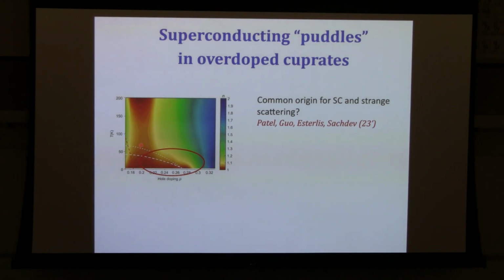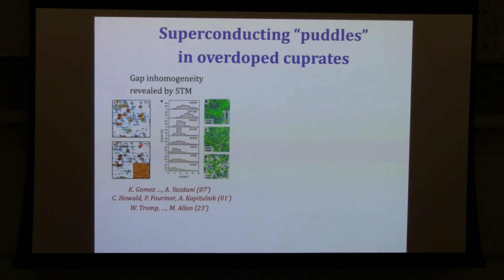What I'm going to say soon, as you guessed, is that for the same reason that some of these superconducting patches survive at high temperature, they also survive in a magnetic field. There's no direct measurement of that at the moment. This is one thing that we want people to try to measure. Is it completely clear that's a superconducting gap and not a different kind of gap? Definitely not from this type of experiment.